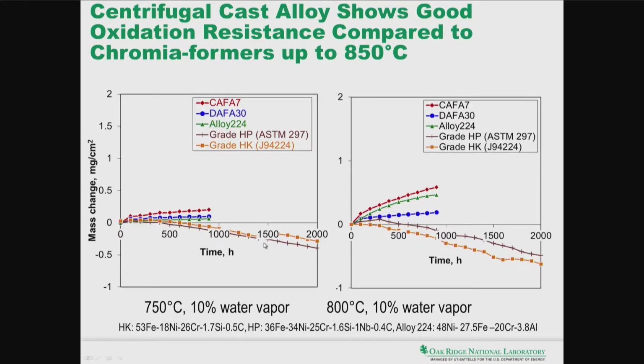So the first set of data you see here is the oxidation resistance as a function of temperature in the 10% water vapor air environment. And what we compare here is the mass change, and there are several alloys here, and let me just walk you through these alloys. The CAFA 7 and DAFA 30 are alumina-formers, and alloy 224 is a high nickel alumina-forming alloy. And as you can tell, these alloys keep a very low mass change as a function of time when compared to the HK and the HP alloys that have shown significant loss in mass, which is related to the spalling.